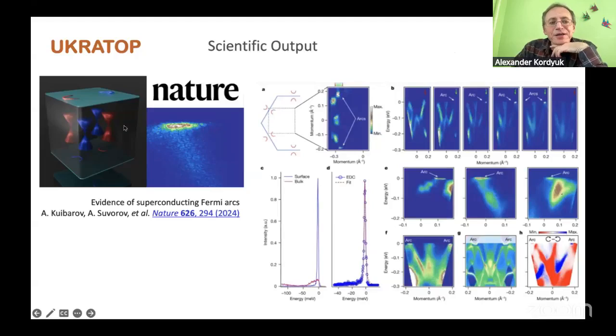You see, this is a cartoon representation of what they observe, and this means that there is some bulk structure, and in the bulk it is a semi-metal, and there is some electronic structure. They are Dirac, but at the surface, the states which are superconducting, they have what they now call Fermi arcs. I didn't like the Fermi arcs very much, which was before. That was about high temperature superconductors.